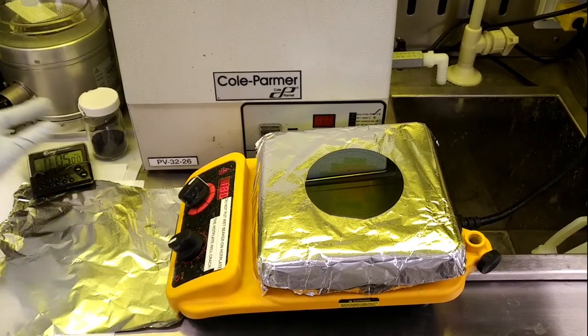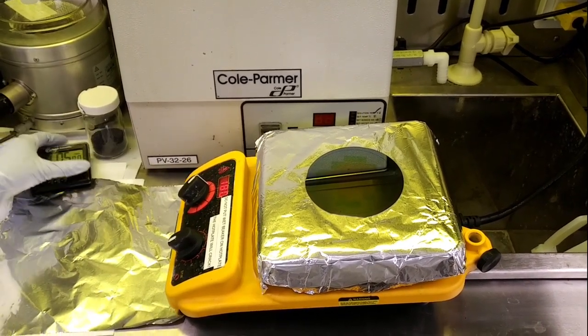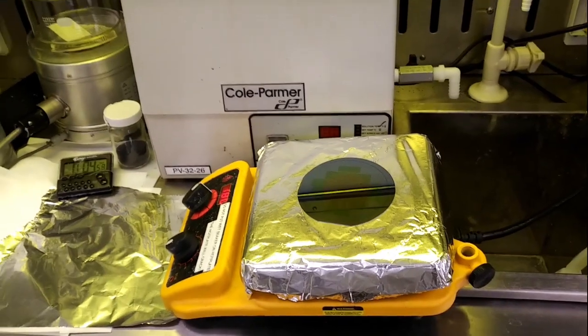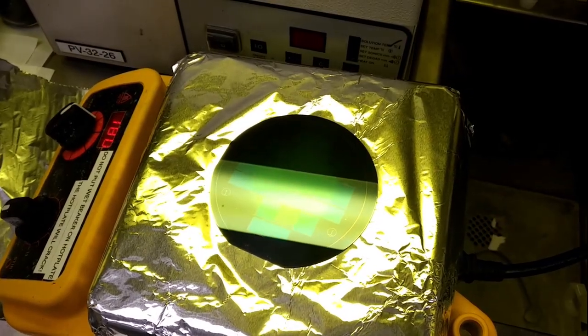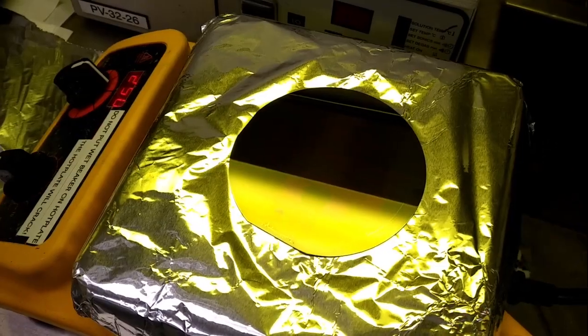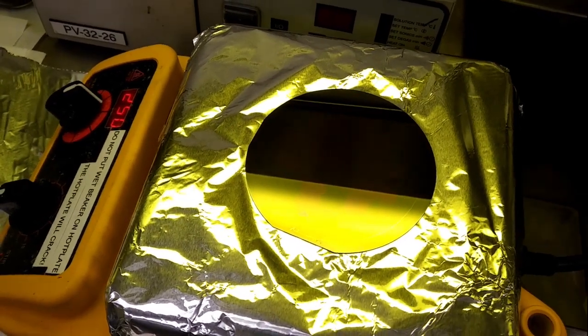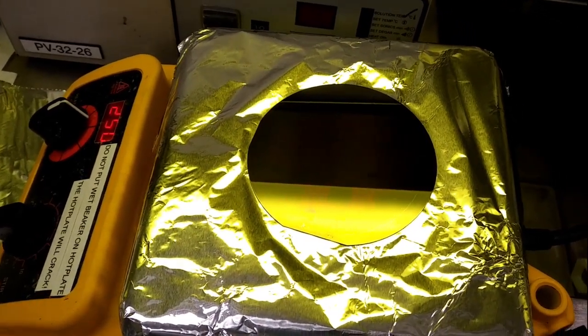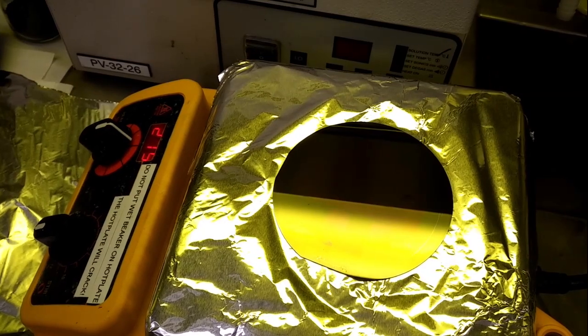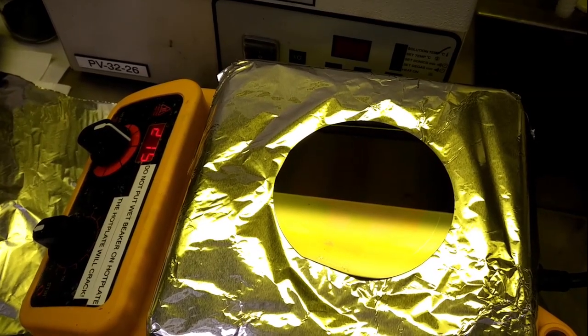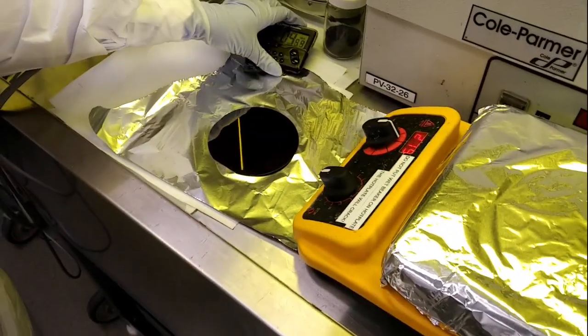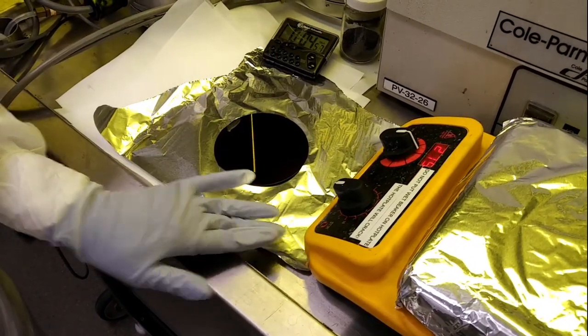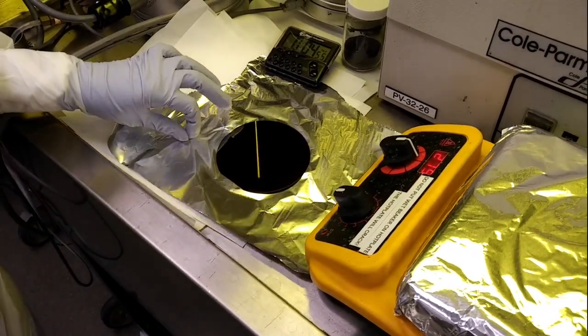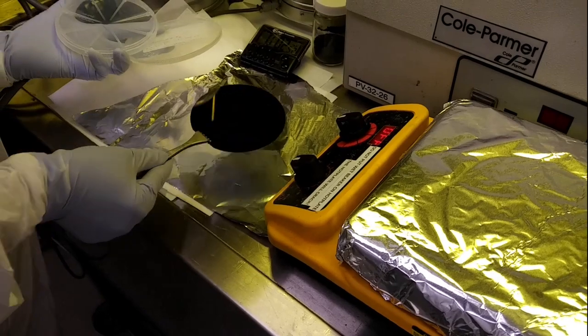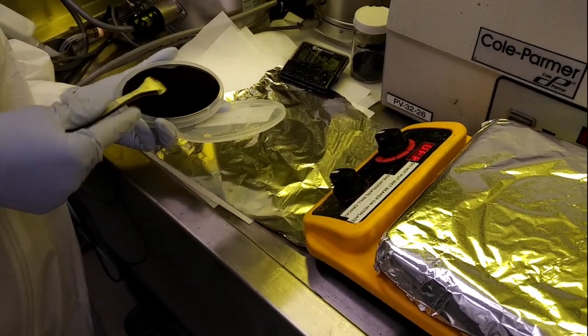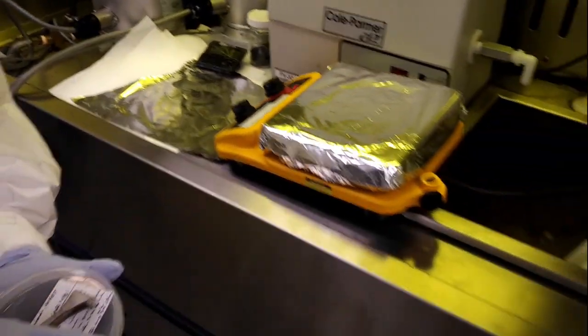First, the wafer is heated to 80 degrees Celsius for 5 minutes. Then the temperature is increased to 180 degrees and baked for another 5 minutes. Then the temperature is further increased to 250 degrees Celsius for 5 more minutes. The final bake is at 275 degrees for the final 5 minutes. At this point, the wafer is removed from the heat and allowed to cool. The wafer is now ready for the thermal process that will drive the dopant into the silicon.